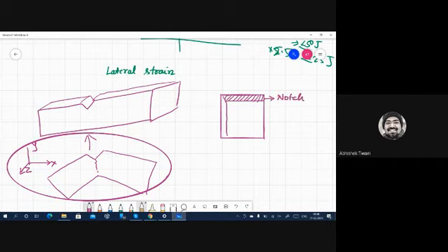And you will not get a complete picture like this, but this is the cross section, and here you will see some fibrous dull region, so it is not very shiny. And then you might see an elevation, a fracture and shear. Whenever there is a fracture at the end, you always see a shear lip.